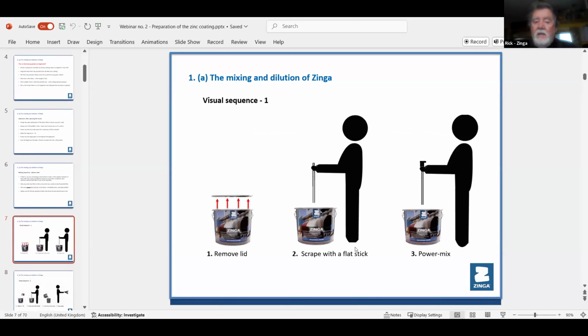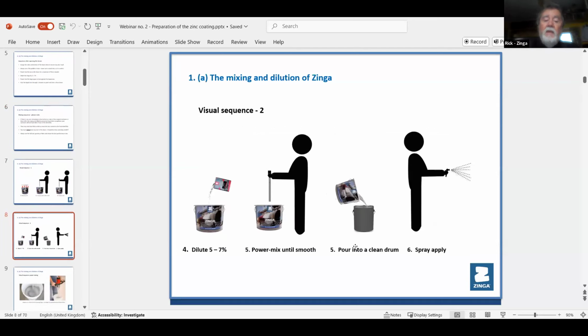This is what we send out in some countries. You remove the lid, you scrape it, you power mix, dilute by 5%, mix it again, and then pour it into a clean drum, and then you spray. We say pour it into a clean drum because if you're spraying a ship or a bridge or something big, it's nice to pour it through a strainer into a clean drum. Then you know everything in that drum is spotless, with no dust or anything in it. That's the only reason we say that.